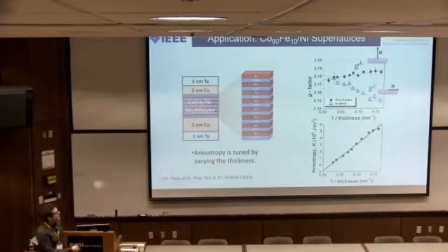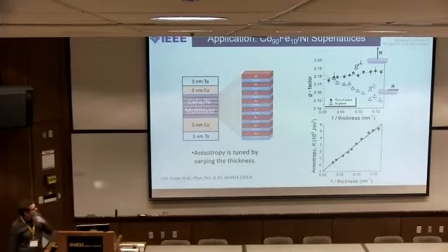And then we go in and apply that G-factor analysis. So this is the G-factor versus 1 over thickness as well. We measure it in the out-of-plane geometry, and we measure it in the in-plane geometry, as shown there. And you can see by those error bars that they're quite tight at applying that analysis.